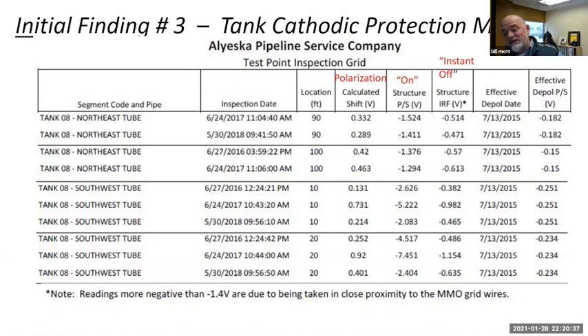All of the 2016 to 2018 data that we were provided for tank 8 suggests that this tank was very well protected from corrosion when related to the 100 millivolt criteria. Everything met the 100 millivolt criteria. The lowest was 131 millivolts of polarization, and the highest was 920. We know the tank's actively corroding, so either there's something wrong with the criteria or there's something wrong potentially with the collection of the data. So we're going to look a little closer at that.